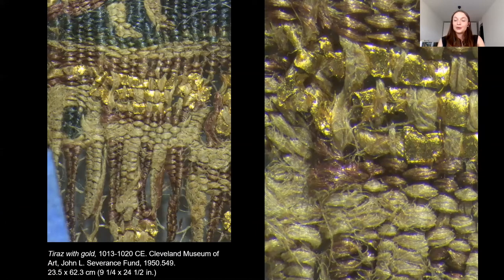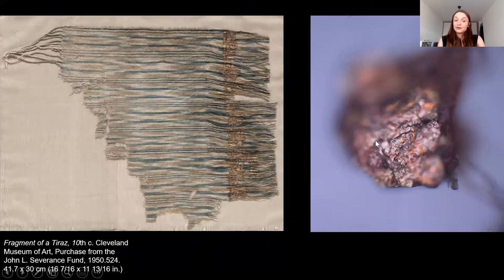Some of the exhibition textiles contain gold decorations. The most common use of gold is called filet, where a thin gold foil is wrapped around a yellow yarn and woven into the textile. The weaver could create patterns and accents as long as they took care not to break the thin foil. You can see a lozenge shape here with the underlying yarn peeking through, and in higher magnification you can see the foil in the central core. Another less common use of gold in textiles is gilding, a practice more commonly seen in statues, frames, and paintings. This piece is a cotton ikat with a gold inscription, and the inscription runs along the fringe of the textile. Ikat is a technique where the yarn is tie-dyed before weaving — based on where the dyer made the ties, a variety of patterns could be produced. In the case of ikat, dyeing and weaving were probably done by the same person to ensure control over the final product.